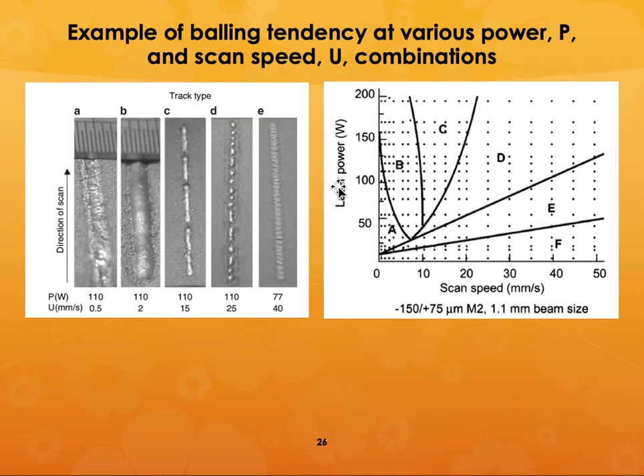So here is an example of the different processing conditions and how the line width can control the balling up. Here you can see that there is a lot of balling up, and here also there is a lot of balling up. This is for a specific type of metal powder, I believe stainless steel powder, and you can see that there is a definite correlation between laser power and the scan speed for bonding, and it will also show that depending upon the processing conditions you have different kinds of surface finishes.